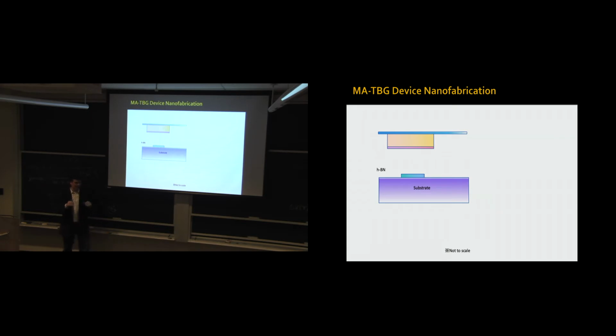Boron nitride is a layered material, also a two-dimensional material. We don't take a single layer, we take something like 20 to 30 layers. It's a very convenient, ultra-flat, ultra-clean dielectric substrate for graphene devices.